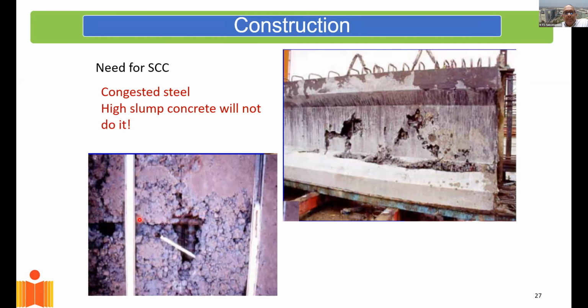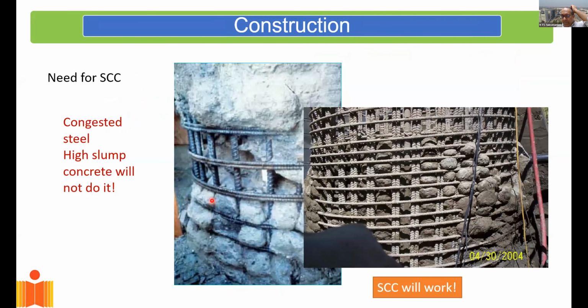So as you can see here, this is heavily congested steel, and concrete just did not fill all the gaps. So at that point of time, a realization came that we have to look at this behavior of concrete and start producing concrete that flows easily. And this is different from slump. And just to show you the need for this self-consolidating concrete, SCC as it's called, this SCC flows very easily, and it would fill all the gaps and cracks and everything that's available.